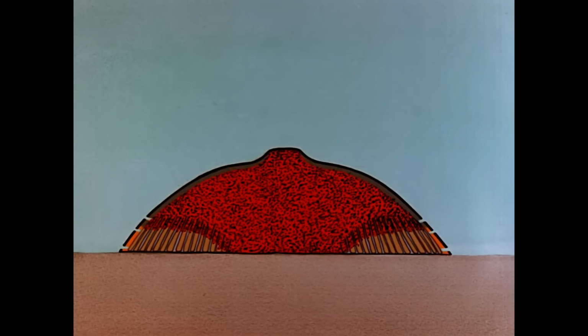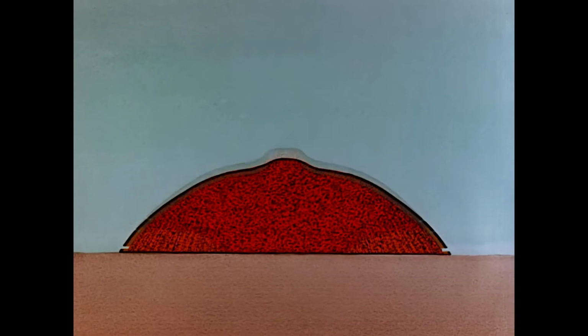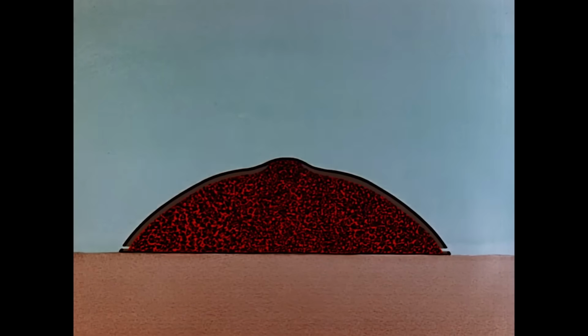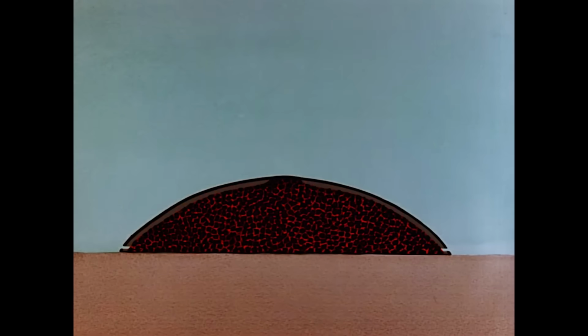The smoke holes now sit just above the draft vents. Coals have nearly reached the hearth. Inside, temperatures reach 270 degrees Celsius. This heat and airtight seal drive off the wood's gaseous and liquid components. What remains is porous carbon, charcoal. The kiln has now charred completely. After cooling for a day, the colliers begin drawing it out.